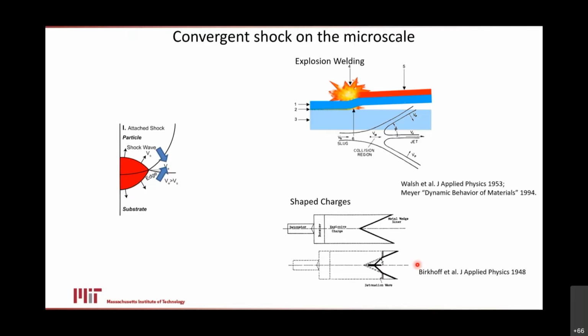Even more directly relevant is an explosion weld. In the field of explosion welding, you take a plate and you put it at an intentional angle to a partner plate down here. And then when you set off this explosion, that V-shape gets you this convergent geometry, and it produces hydrodynamic jets that shoot out the center. And importantly, in the case of explosion welding, this jet is actually a functional feature of the process. So the hydrodynamic jet sort of cleans off the interface. It crushes asperities and it breaks up oxides and that kind of thing so that you can actually get an explosion bond that is metallurgical.